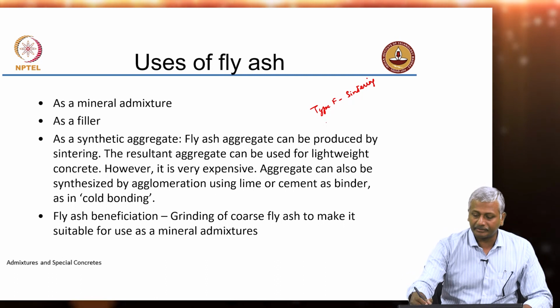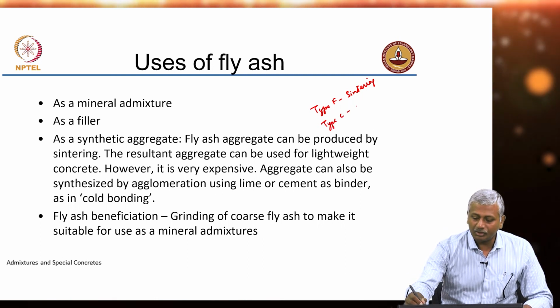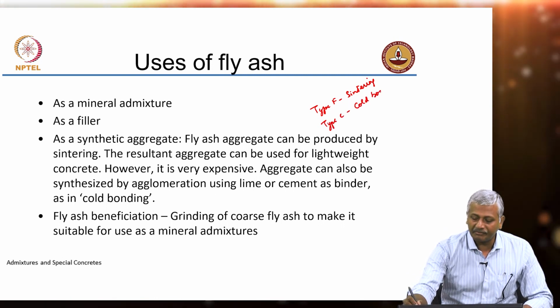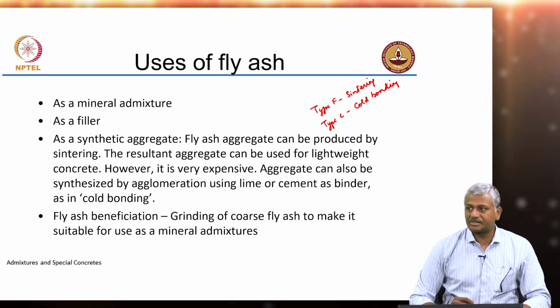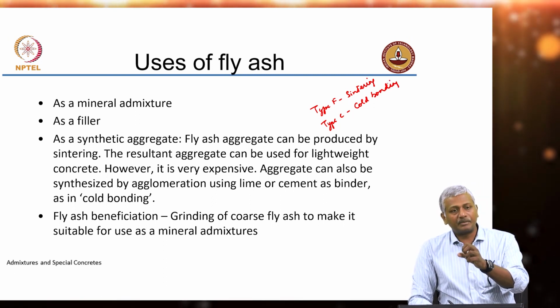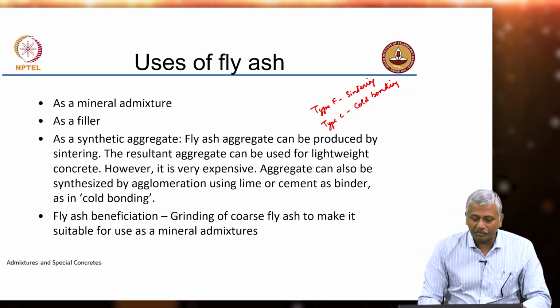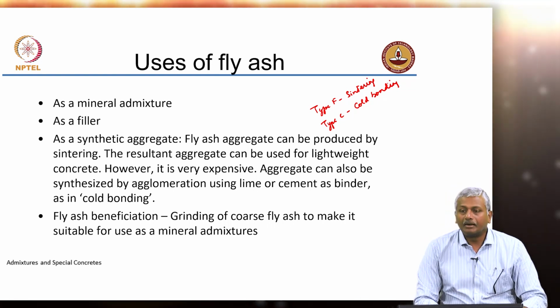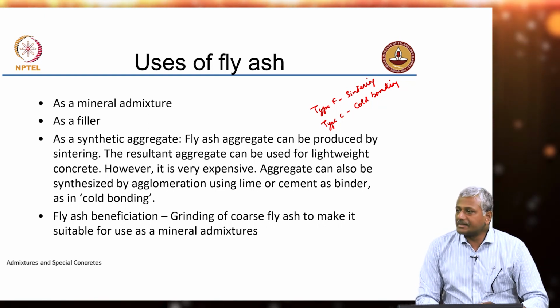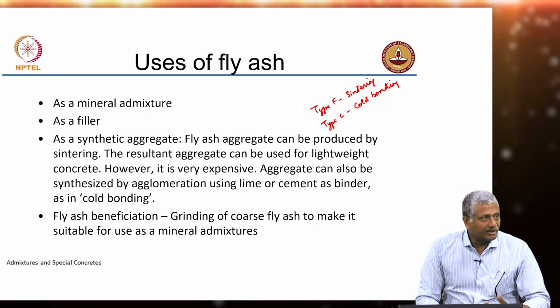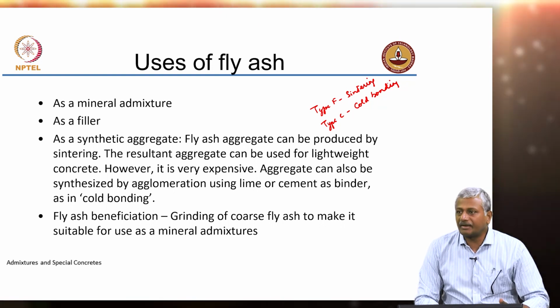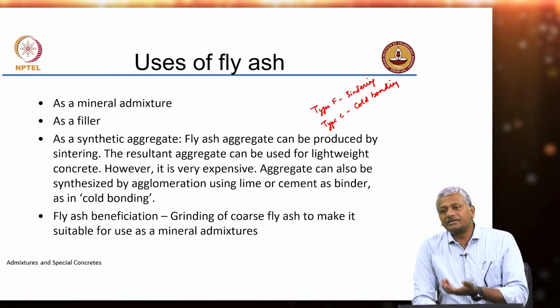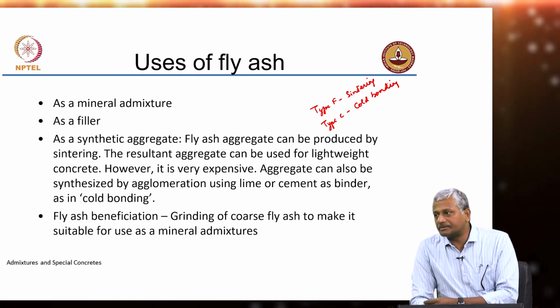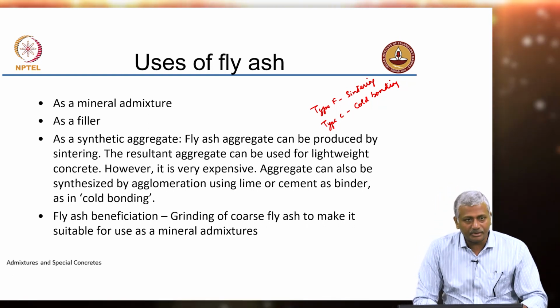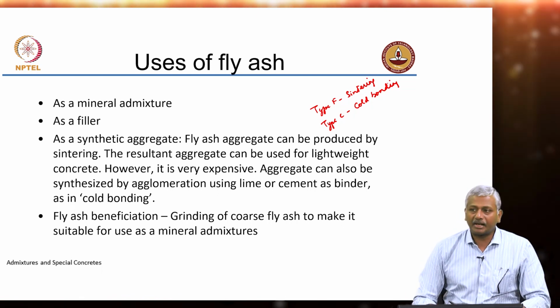Typically Type F is done by sintering, just like you do for bricks, and type C fly ash we do with cold bonding, where we rely on the hydration of the fly ash itself to actually lend to the hardness improvement of the pellet, and finally we produce the pelletized aggregate. The bottom ash, as I said, is not reactive. You can take it and grind it finer and cause it to beneficiate the fly ash. That means you are harnessing the reactivity from the fly ash by grinding it finer, okay. Obviously, you need to justify the cost and the performance that you are likely to get out of this system.